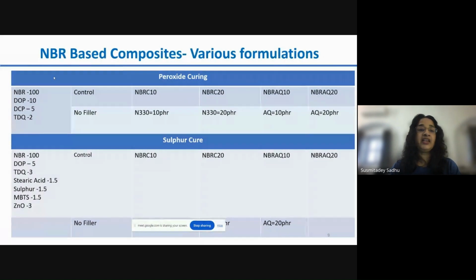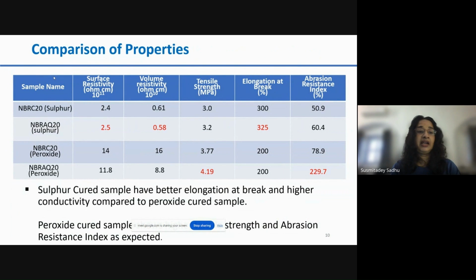So in the next phase, we have mixed this in NBR at two different loadings, that is 10 phr loading and 20 phr loading. And for comparison, we have also taken untreated carbon black at 10 and 20 phr loading. For comparison purposes, we have used both peroxide curing and sulfur curing. So the result shows that the aqua regia treated carbon black filled at 20 phr loading with sulfur crosslinker is showing the highest conductivity, both surface and volume.